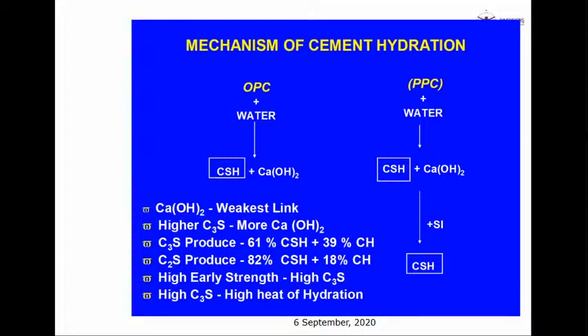But this problem is mitigated to a certain extent when you use blended cements, because a part of this calcium hydroxide, not entirely, remember, part of this calcium hydroxide is again reutilized by silica, which is available in the form of the admixtures, additives, the mineral admixtures you have used, basically the pozzolana materials, the fly ash or the slag. So part of this lime is again combined with silica, and it again forms a small quantity of calcium silicate hydrate, which is why blended cements are more durable, as well as giving a little bit extra strength in the long term. This is because of the secondary hydration which takes place.